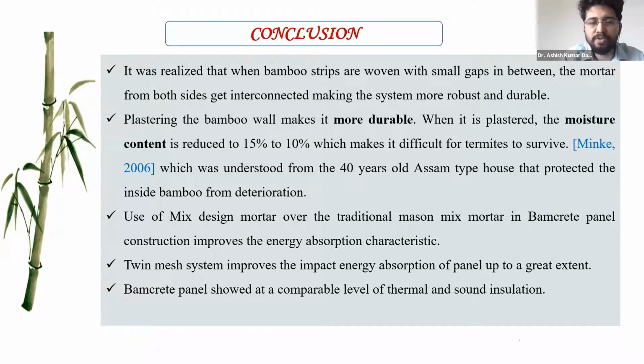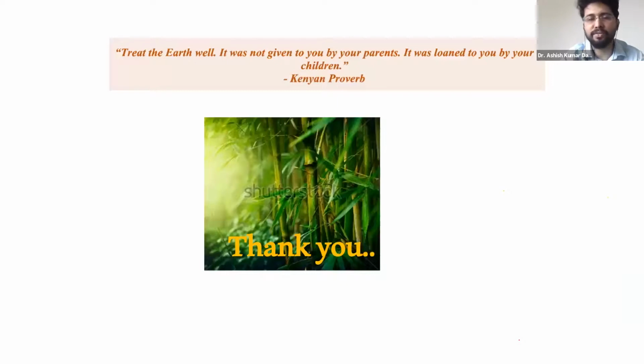So the twin mesh system improves the impact energy to a great extent, as we saw in the impact energy test. But the energy absorption with static loading, especially monotonic loading, was a bit less, even less than the single mesh concrete panel system, because of the lack of interconnected mortar from both sides of the woven bamboo strips. The mix design of mortar over the traditional mason mix in the concrete panel construction improves the energy absorption capacity and characteristics. Thank you.